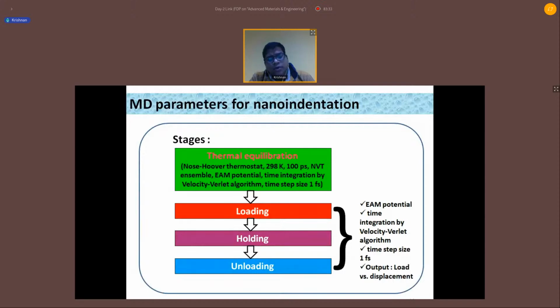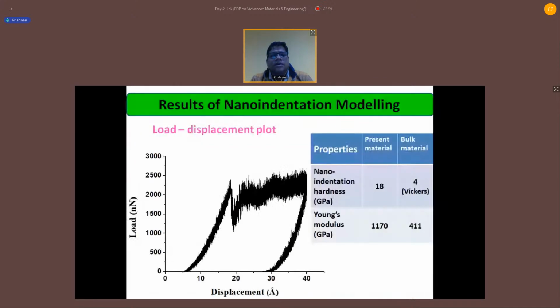we calculate the Young modulus, that is basically S into root pi by 2 into beta into root A. Before the Young modulus calculation, we have to check the critical height of the surface, that is h max minus epsilon P max by S. That is a well-established equation designed by Oliver and Pharr. So in this way, we can calculate the hardness and the Young modulus from the load displacement plot. This is the load displacement plot, and we have calculated the hardness and the Young modulus, which is quite more than the bulk material.